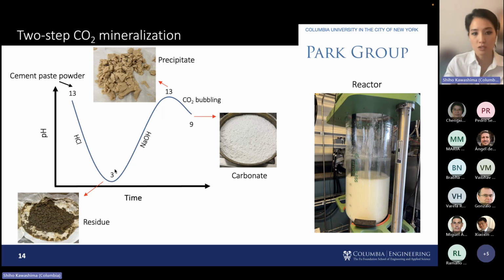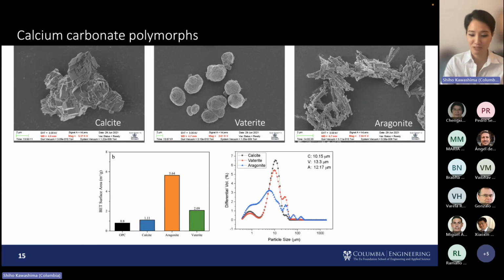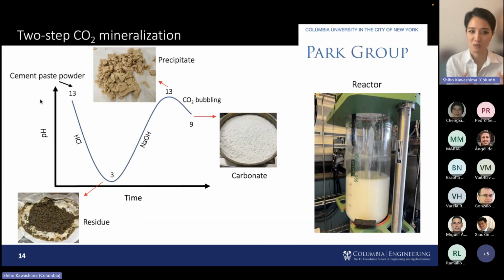And then you employ this pH swing where you drive the pH back up, and then that's where you extract out your precipitate. And so that's where, again, the remaining impurities are: silica, alumina, iron, a little calcium gets in there. But then you have a pretty pure calcium system. You apply CO2 bubbling, and you get your calcium carbonate. So chemistry is pretty amazing, where you start off with this recycled hydrated cement paste, and then you can separate the silica and then obtain this very pure form of calcium carbonate.